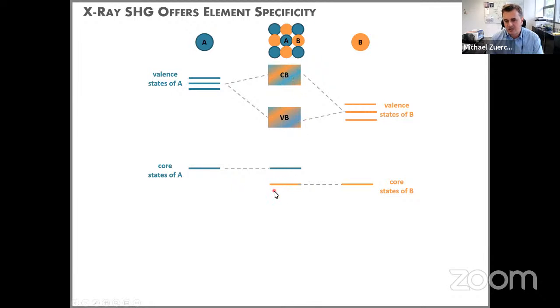Say, if you do X-ray absorption spectroscopy, you probe the transition of a core electron from a certain element with a resonant transition into, say, empty conduction bands, giving rise to an absorption edge. So this is what we typically do in X-ray absorption spectroscopy to study specific properties of one element in a complex system. So now what we set out to do is to investigate whether or not it is now possible to do this.